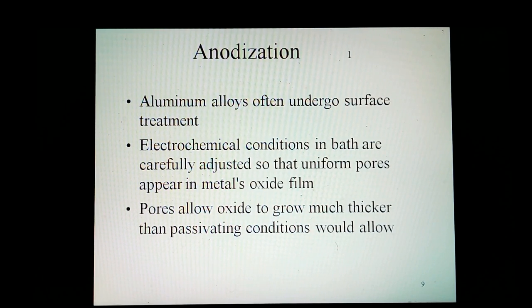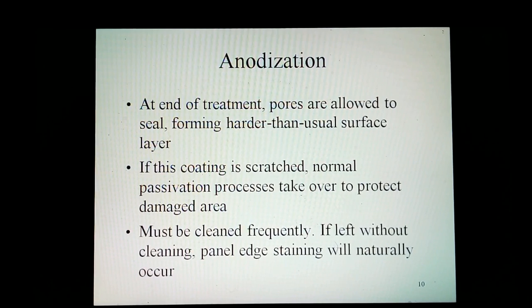Anodization. Aluminium alloys often undergo a surface treatment. The electrochemical conditions in the bath are carefully adjusted so that uniform pores several nanometer wide appear in the metal's oxide film. These pores allow the oxide to grow much thicker than passivating conditions would allow. At the end of the treatment, the pores are allowed to seal, forming a harder than usual surface layer. If this coating is scratched, normal passivation processes take over to protect the damaged area.